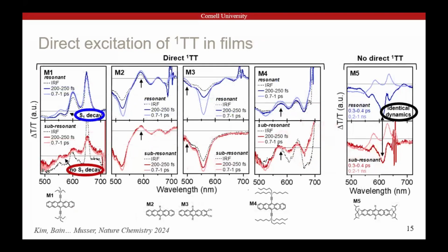Same thing applies in films. Most of our films, these M1 through M4, they show that when we pump in the blue, we get singlet turning into triplet pair with the very clearly identifiable time scale. Pump in the red, and the only thing we can see is the triplet pair state. But this film, this M5 with very bulky side groups, no matter where we photoexcite, we always get singlets and they slow and turn into triplet pairs on their own chosen time scale.